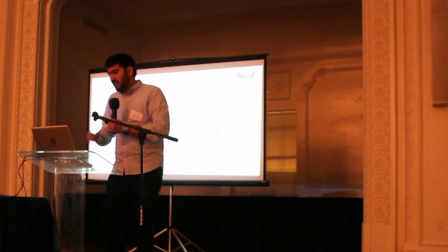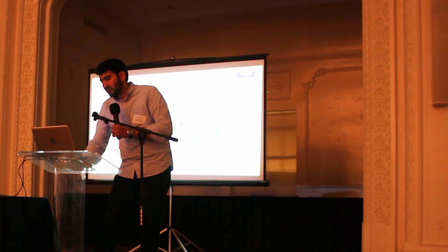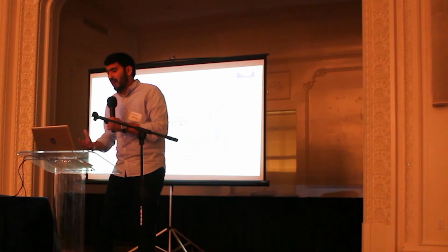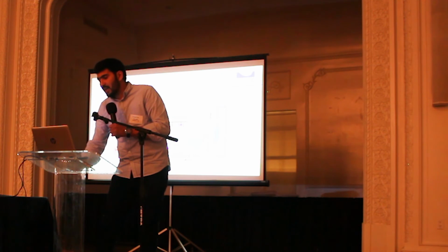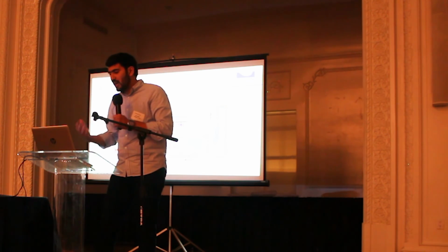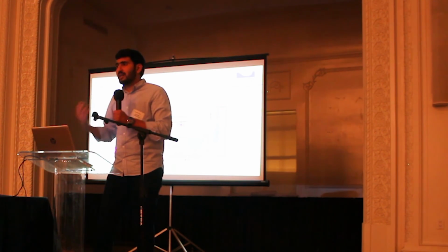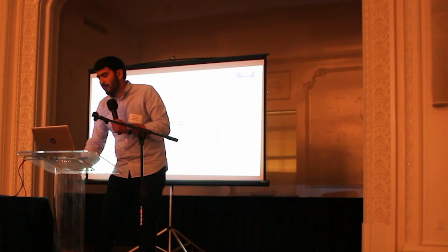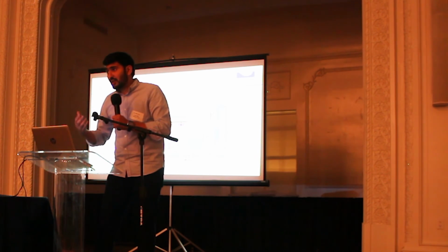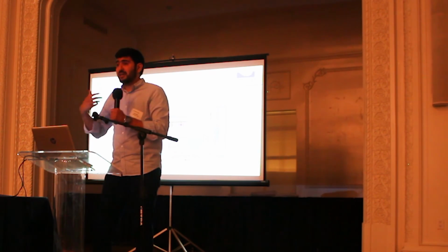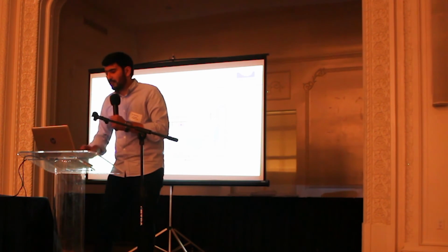As we can see here, the main components of the testing facility include the tank that acts as a source of the brine solution. Here we have a pH section where we can measure pH at the beginning, during, and at the end of the test. We have a circulating pump, and then a bypass section where we can measure the flow rate. And then here we have the test section. This section has the single test cell where we put the steel and different material samples.